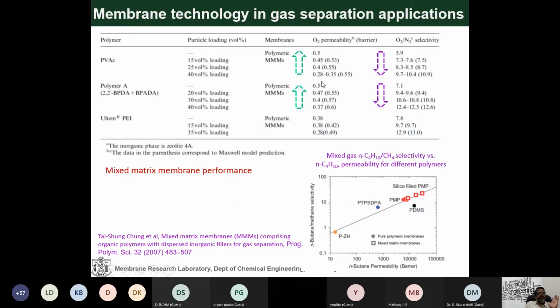This is an example of gas separation using a mixed matrix membrane. Here the oxygen and nitrogen permeability is increased by adding different loadings of the particles. Then the MOF for gas separation: the ZIF hollow fiber membranes are from our research group, developed by Sasi Kumar. This work was published recently in Separation and Purification Technology.